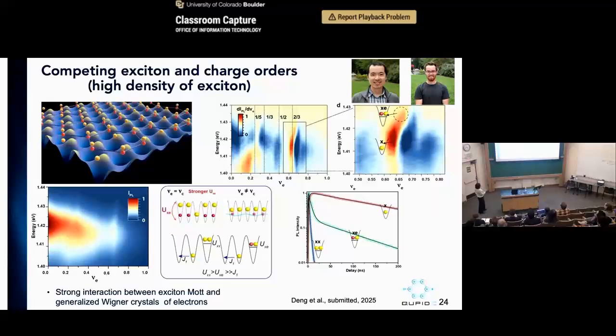If we take the derivative of this, you can see all these different special locations of the charge orders, like 1/5, 1/3, 1/2, 2/3, and so on. But what's more interesting is that we can now also see a new emission, for example near 2/3 filling. It's slightly higher in energy than the lowest exciton band, and we think this comes from when the exciton has to co-occupy with a charge. Because of the repulsive interaction between them, they also have to occupy a higher energy.